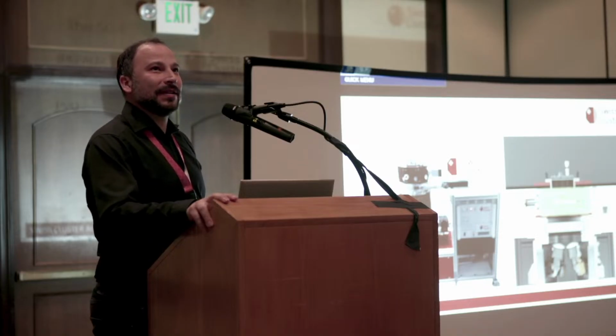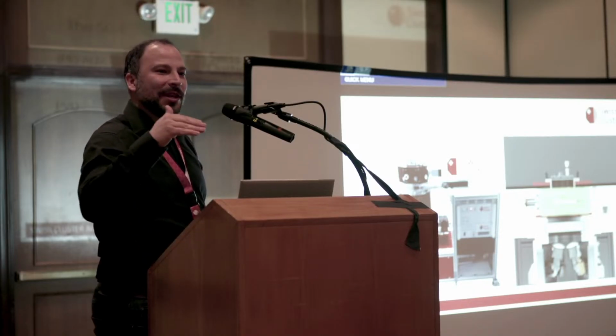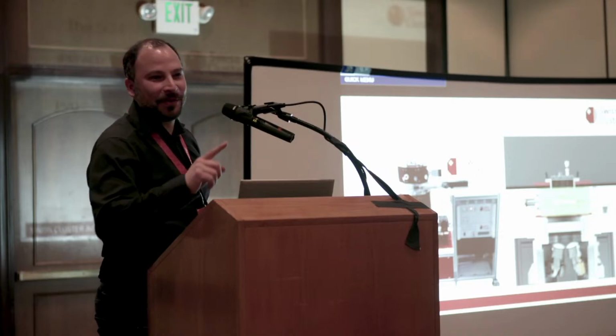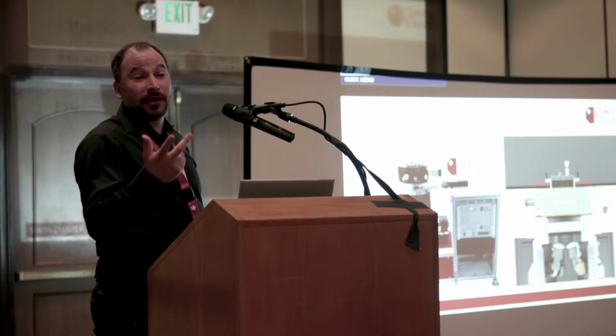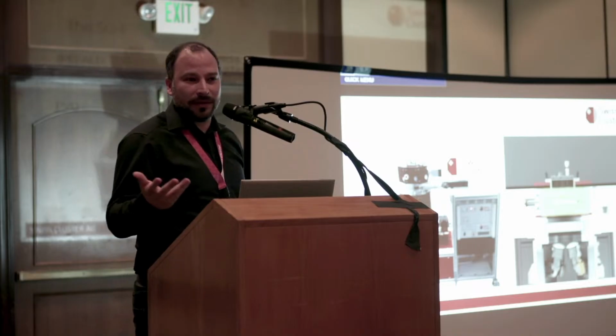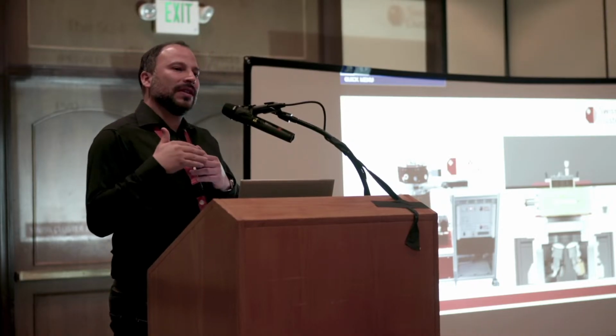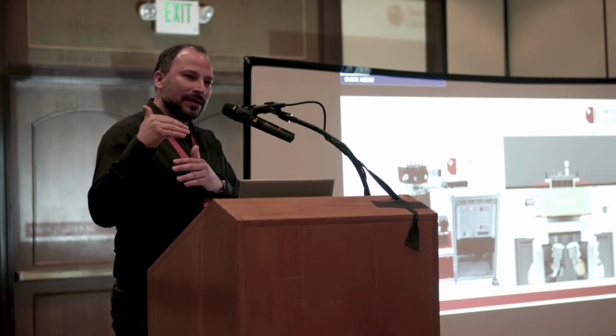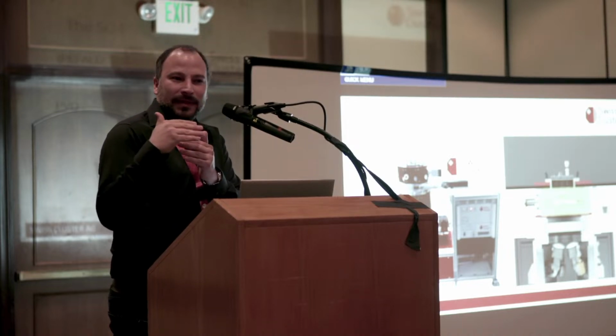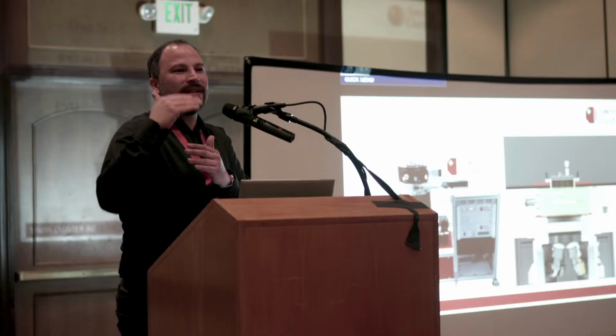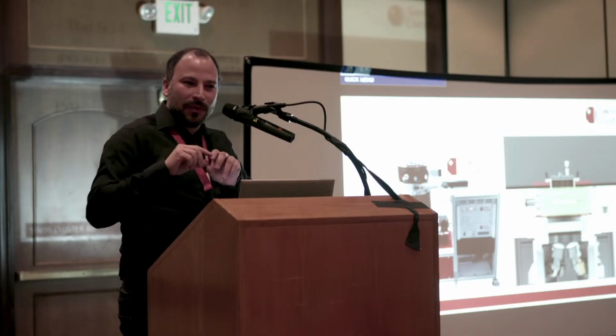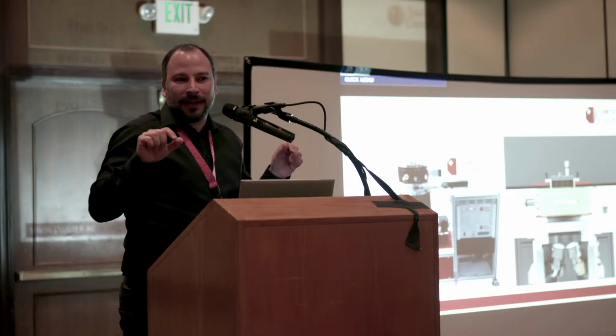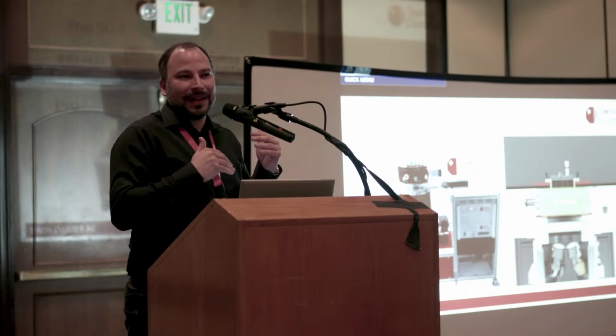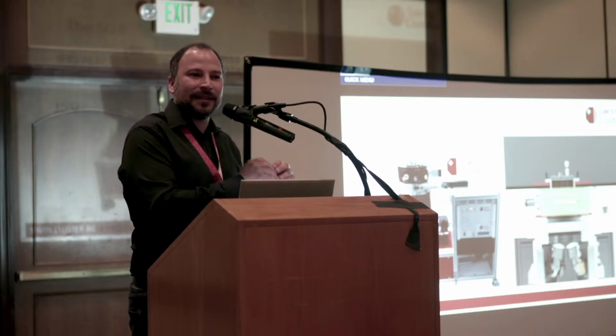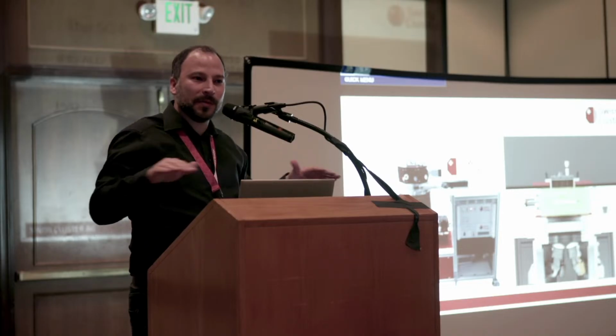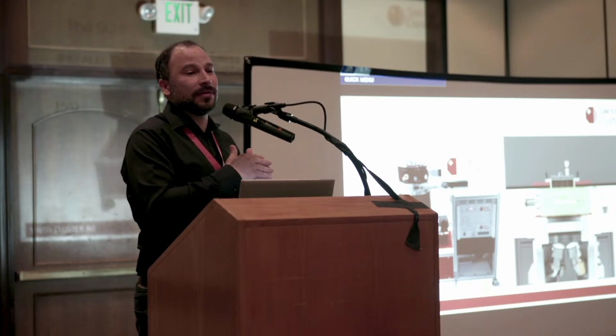So what's the difference between doing a multilayer just by sputtering? That was the question that I was waiting for. Of course, you can do aluminum oxide or any other oxide by reactive sputtering, right? But when you do this, you're introducing oxygen, and the aluminum oxide, for instance, if you're doing it on aluminum, will continue the same microstructure, the same columnar growth. It will still be full of defects as PVD grows, right? So that's where ALD shines, because you really have a pinhole-free film that conforms over the whole surface and really breaks this grain growth.